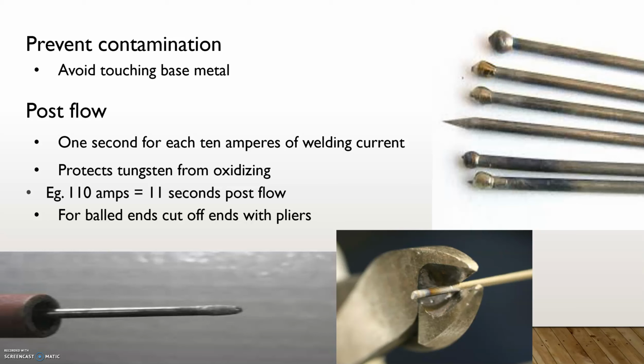Post flow is very important for protecting a cooling weld, and it is also important for keeping the tungsten healthy. For every 10 amps, there should be 1 second of post flow time. So in the example you see on the screen, for 110 amps, you would have 11 seconds of post flow coming out of the torch.